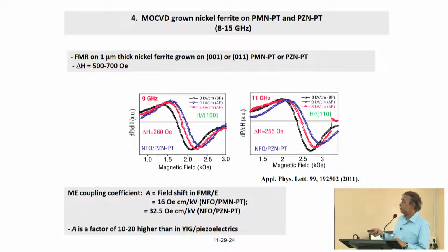just to demonstrate that this is not something you would like to use for any tunable device applications. And this is on PZN-PT, and the film on PMN-PT had rather poor tunability compared to this, but PZN-PT has a much higher piezoelectric coefficient compared to PMN-PT, but in spite of that, this tuning is no good as far as device application is concerned.